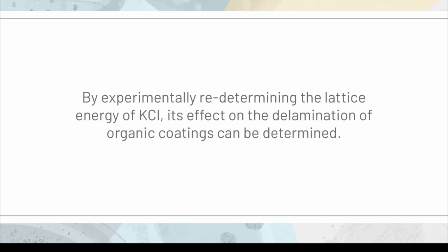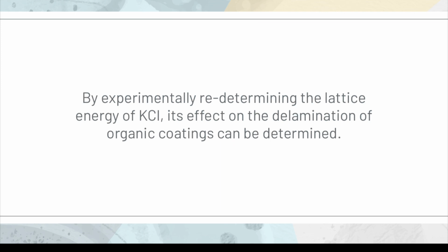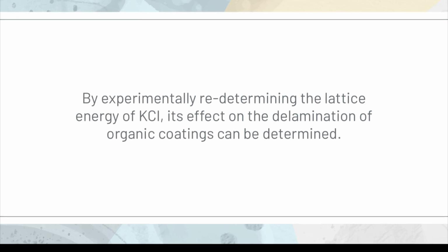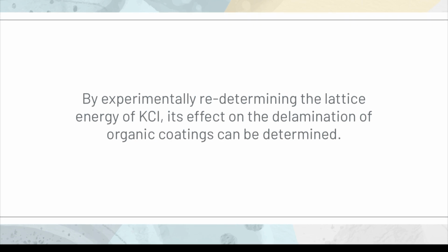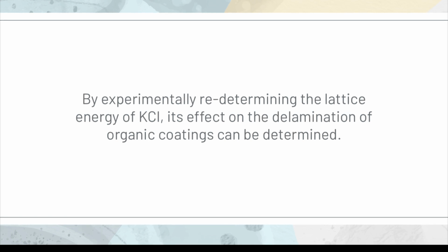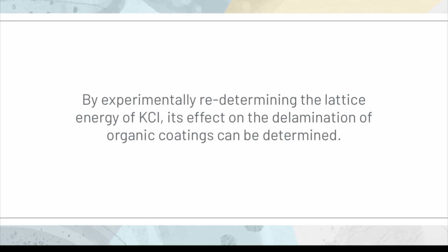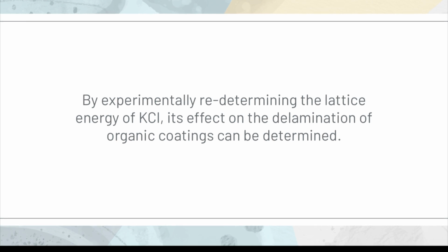Thank you, Rin. Now, to review the contents of our proposal. It is impossible to directly determine the lattice energy of potassium chloride experimentally. However, using the Born-Haber cycle, we can indirectly determine the lattice energy of potassium chloride by determining its enthalpy of formation. This can be achieved using calorimetry to find the enthalpy of dissolution, which can then be used to calculate the enthalpy of formation, which, relatively speaking, is a rather cost- and time-effective determination method.